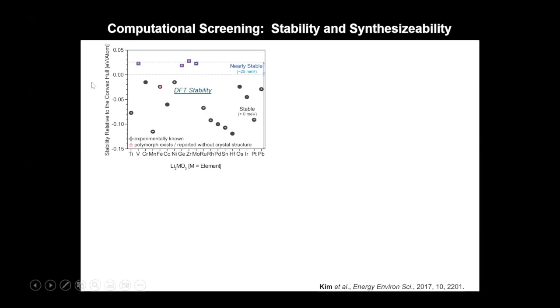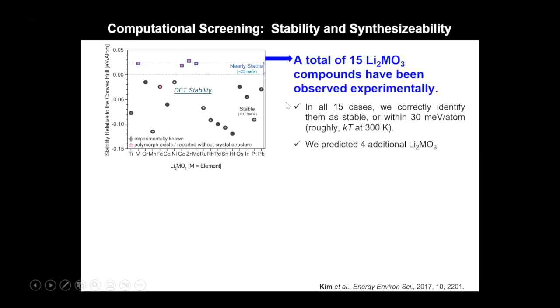But the bottom line is that if you look at all of the experimentally observed compounds in this class, all of them are calculated via DFT either to be thermodynamically stable or very close to stable. This is an interesting validation point, and it gives us a clue that thermodynamic stability is maybe a good screening criterion in this idea of computational screening.